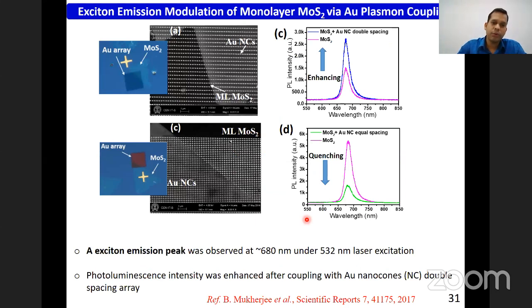So we start with monolayer MoS2 on a silicon dioxide silicon substrate, and then we fabricate a gold nanocone array on top. There we select two different types of array. One is double spacing and one is equal spacing. And what we observe under 532 nanometer excitation is that the photoluminescence at 680 nanometer gets enhanced for the double spacing array, and it gets quenched for the equal spacing array.